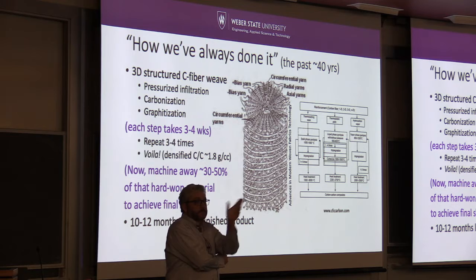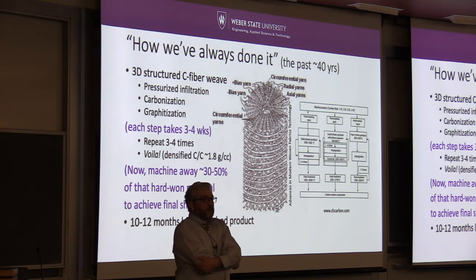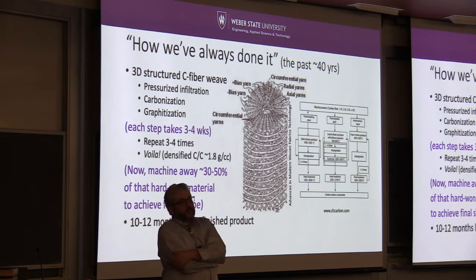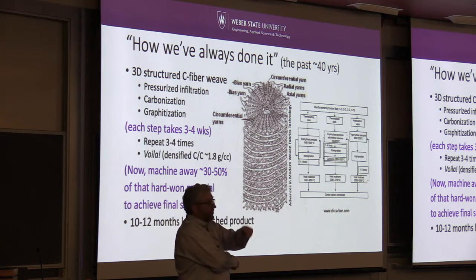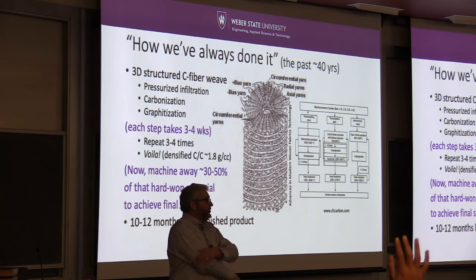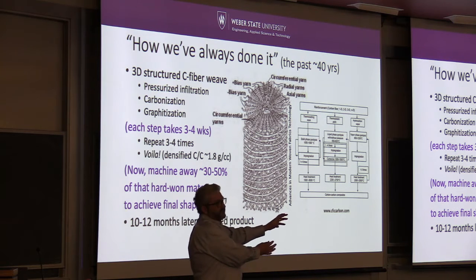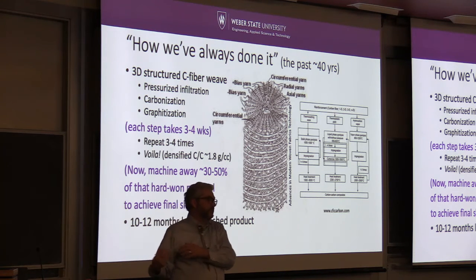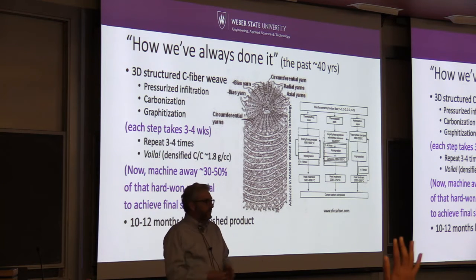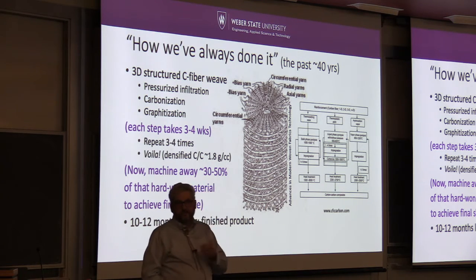Any ideas? Please. Is this an oven cure or an autoclave? It's like an autoclave, but a heated autoclave. Are you talking about the infusion or the subsequent steps? They're heated. Some of them are under pressure. The infusion is under pressure. The carbonization is under vacuum. Heated. So you're trying to get this resin into the system. You're trying to get the volatiles out of the system. Let's just talk about the resin going in. What kinds of things would you do?